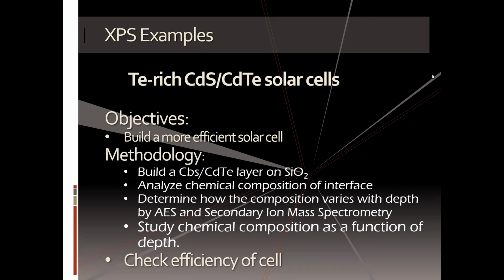But this is what they did. When you build a solar cell, like this one with cadmium and tellurium, you do the chemistry and make your film, and usually it is not a thin film, it's a thick film. How do you know that you mix the elements well? How do you know that you have a uniform mixture of the elements? Well, what we decided to do is to examine the surface, then get rid of the surface and examine it again, then get rid of the next layer and do it again. And we kept on doing that until we went all the way to the substrate, to the piece of glass.